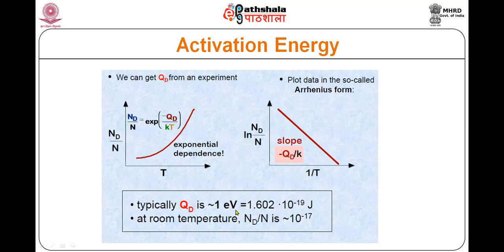Its order was also told to you. It's typically 1 electron volt. Typically 1 electron volt means it can be 0.2 electron volt, it can be 3 electron volt, somewhere around this order. And at room temperature, the defect concentration is 10 raised to the power minus 17. So you see, this is also very low. Our approximation we were talking about in the last slide is going to be very correct, because you can see this ND is very much less than N. It tells us that if you have 10 raised to the power 17 atoms, there will be one defect in those atoms. So a very small number of defects is there at room temperature.